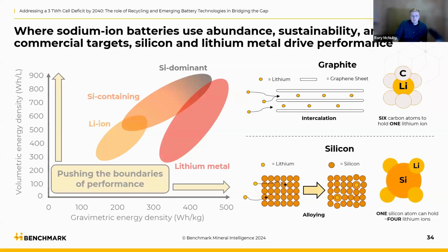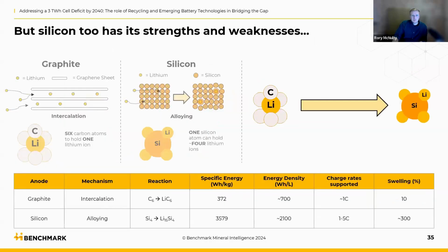If we look at how silicon intercalates or interacts with lithium, it's through an alloying mechanism. So lithium here doesn't intercalate into the silicon structure. Instead, it physically interacts with the silicon, and each silicon atom can store almost 4 lithium ions reversibly. It's around 3.75. This increase in lithium storage enables silicon to have a much higher capacity than its graphite alternative.